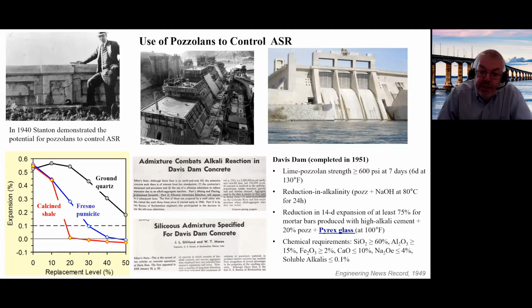The Davis Dam took advantage of pozzolans and actually specified pozzolans to control ASR. So back in 1950, engineers were using pozzolans in major structures to control ASR. And the work that was conducted by Gilliland and Moran, who basically developed the idea of using Pyrex glass as a standard reactive aggregate in mortar bars, demonstrated that one of the specification requirements for the pozzolan used in the Davis Dam was that it could control ASR in the Pyrex mortar bar test. And they also had chemical requirements for the pozzolan there, which is fairly interesting. Minimum quantities of the silica, alumina, and iron, and a maximum quantity on both the calcium and the alkali content.